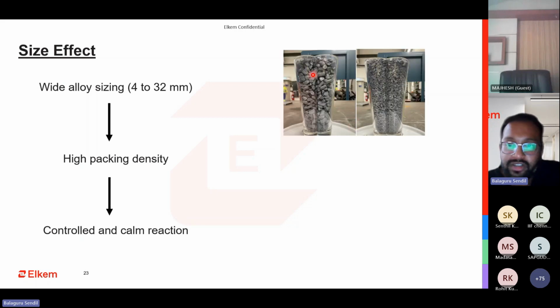So if you look at here, these are the same volume. I have a container in which the volume is the same, and the shape and size is also the same. This is, I would say, a 10 to 20 or a more narrow one, and this is a more coarse one. This is from somewhere between 4 to 32. It's a wider sized FSM. You can see for yourself how nicely this is packed and how nicely this is packed. Here, the chances of the metal to go high is quite high. Here, the chances of the metal to go down is very gradual.